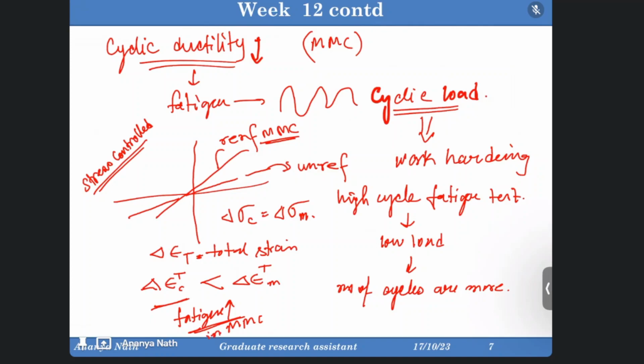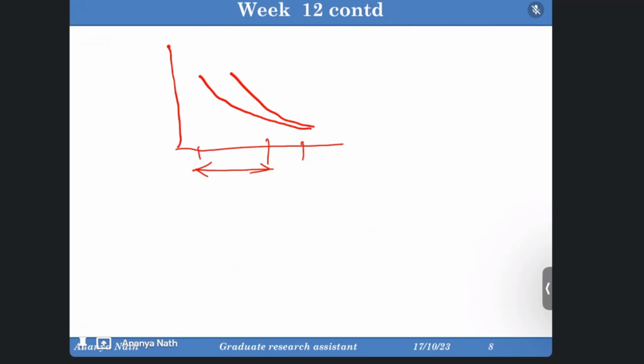So the difference in the fatigue life is more pronounced at the lower stress level, because when the material has experienced a lot of cycles, in case of high cycle fatigue, at that stage it will act more like the unreinforced one. So the curves touch each other at the high cycle. Up to this many cycles, there was a lot of difference in the reinforced and unreinforced, but at that high number of cycles, the difference will be reduced, obviously, because there will be a lot of strain generated in the composite as well, which is giving us the result of the failure.